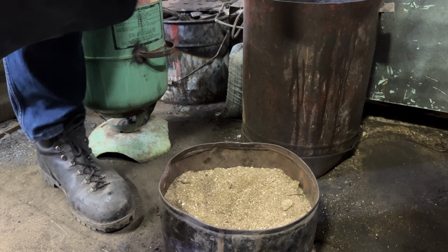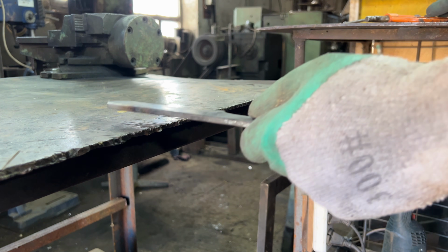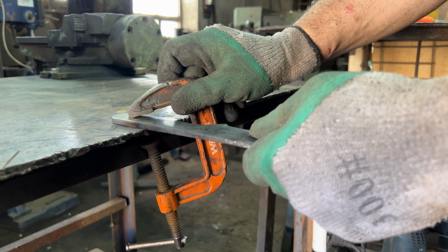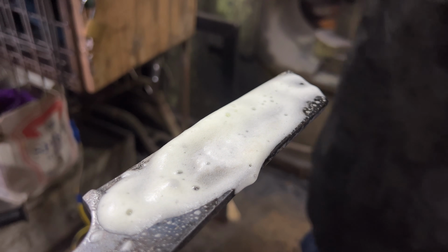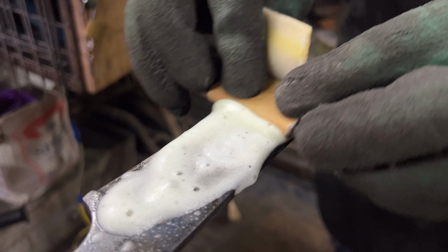Heating for the quench. The blade comes out of the forge with a uniform glow and into the oil. A sharp transition, smoke, and a flash. The oil boils around the metal. This is where the steel gains its hardness. Then, into the sand to strip the oil residue from the surface.